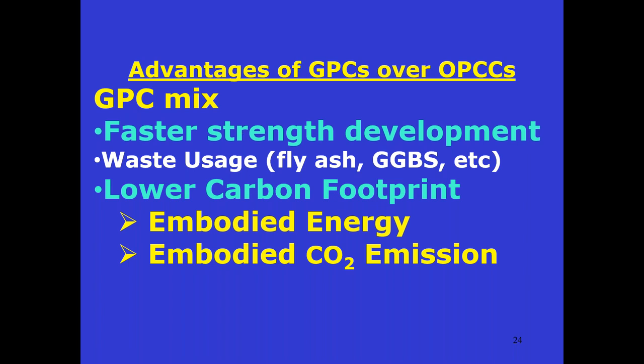Okay, because it is a polymerization reaction. And we are using waste. This is an advantage, because your fly ash, blast furnace slag, and so many other things. And most important is embodied energy is reduced. Okay, embodied energy is how much energy goes into making 1 cubic meter of the concrete till it is put in the site. So that is called embodied energy, and it involves production as well as transportation, placing, everything involved in that energy. And this can be calculated, not by us, numbers are available for every operation, and you can do it.